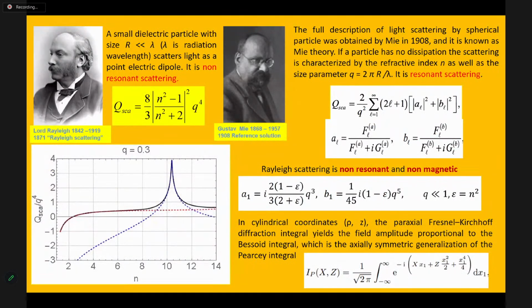Then the next step was done by Lord Rayleigh, who analyzed the scattering of a small dielectric particle with size much less than the radiation wavelength. The result was that this particle scatters like a point electric dipole, and it is non-resonant scattering. The scattering efficiency is given by this formula, where q is the so-called size parameter, the ratio of radius to lambda multiplied by 2 pi.